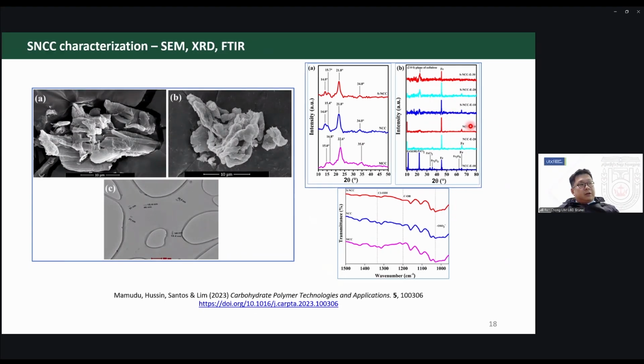Once we prepare the coating, we coat it on the metal tube and put it into a corrosion chamber containing sodium chloride for 30 days, then we take it out and do an XRD. What we see is that the ones with the sulfated nanocellulose don't show any chloride peaks. We only see them at the low concentration of nanocellulose, so we're quite confident that our hypothesis was working.